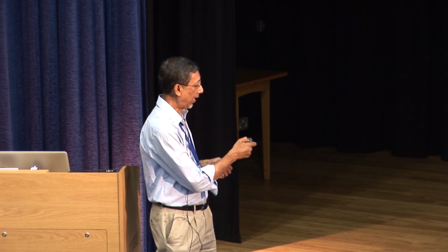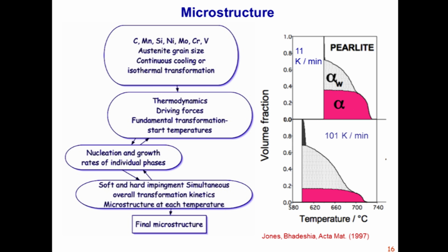Normally, to most of you, it is not a surprise that from cooling rates, composition, and austenite grain size, you predict, you calculate actually microstructure. Many of you have been doing this for a while, so I would tell you that we tried a similar exercise where we consider the driving forces for different phase transformations, and we look at the transformation start temperatures from all these parameters. We consider nucleation and growth of individual phases simultaneously. And then we look at the soft and hard impingement simulation and overall transformation kinetics, and we get microstructure.